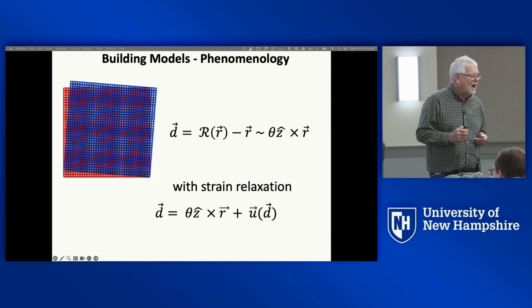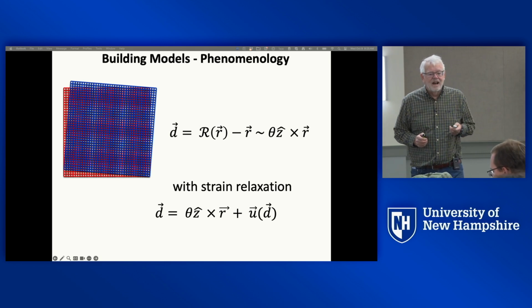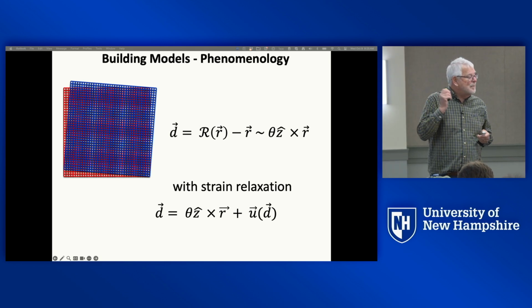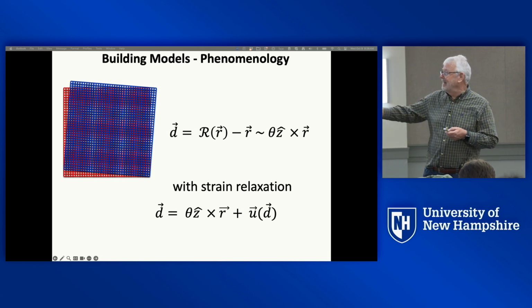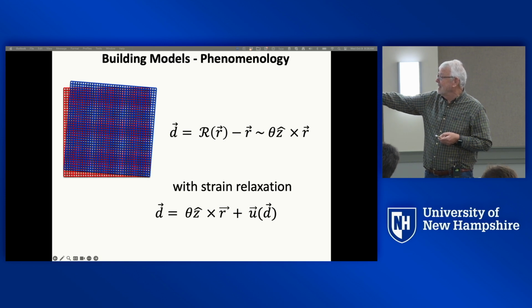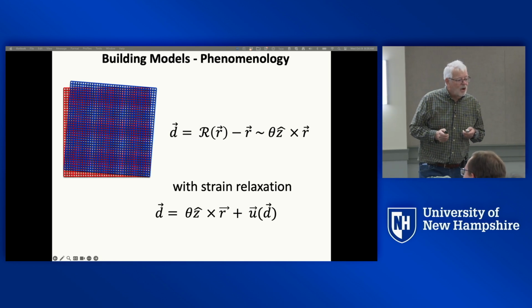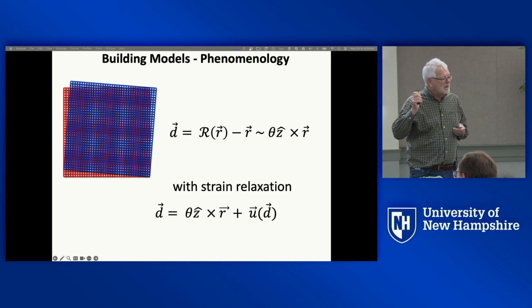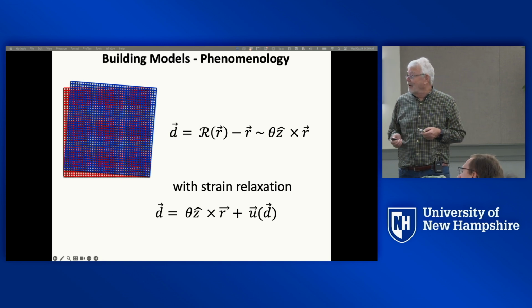One number describes, in this smooth argument, the dependence of the Hamiltonian locally on stacking. And if I have this twist-type Moiré pattern that's produced by rotation, then it turns out the displacement, for a rigid rotation by a small angle, would be linear in coordinate. The displacement modulo a reciprocal lattice vector is periodic. It has the periodicity of the Moiré pattern.